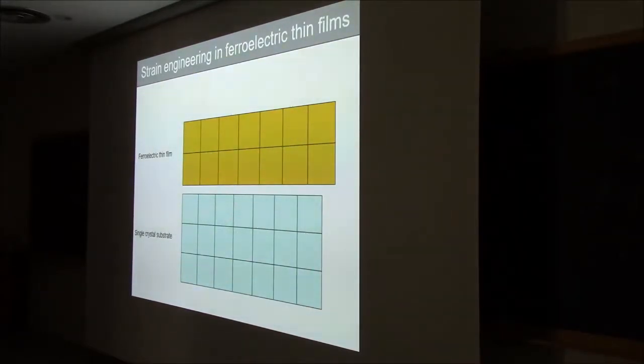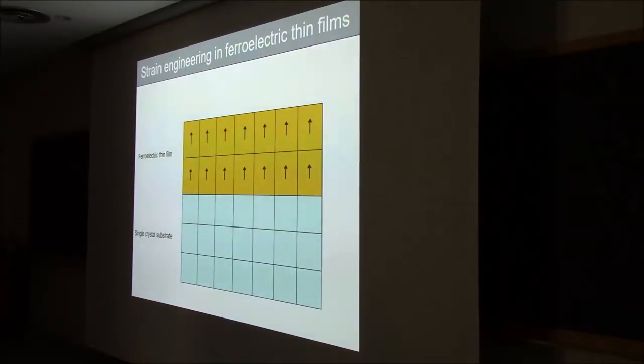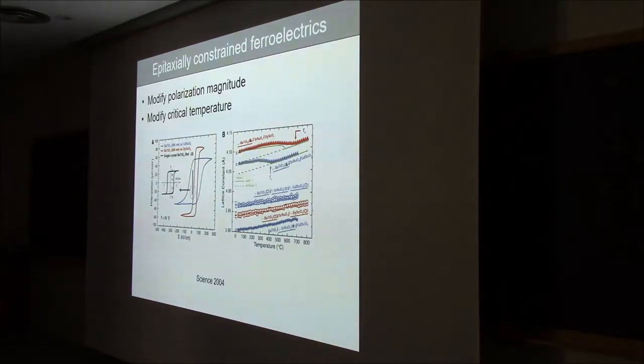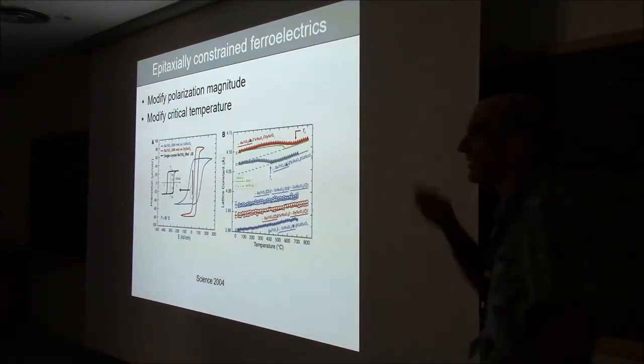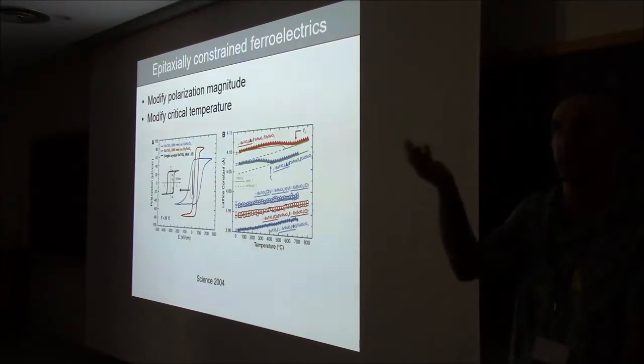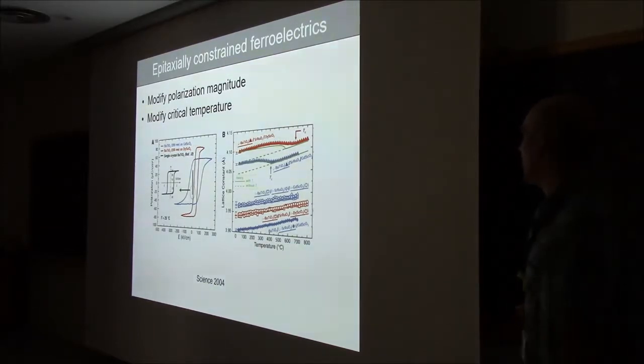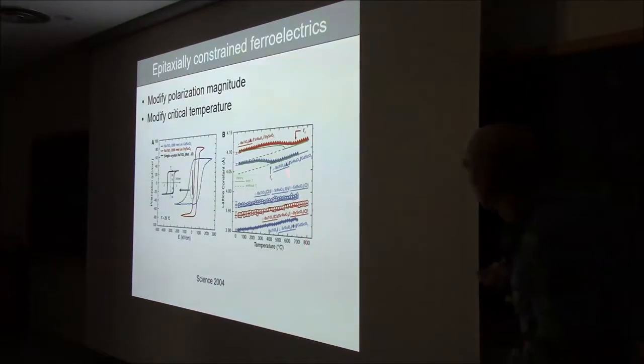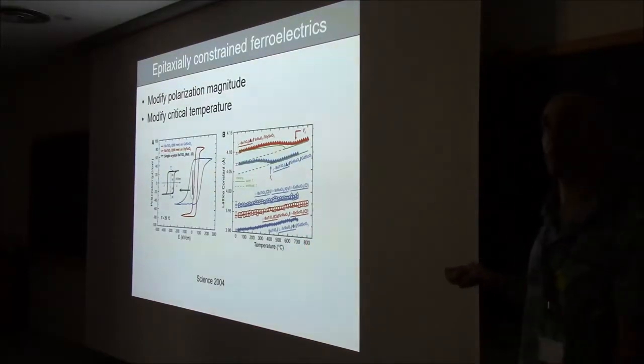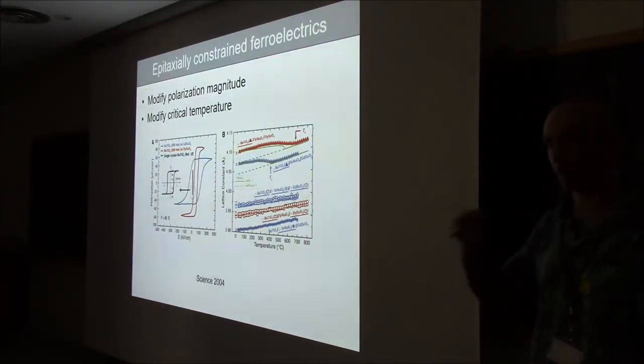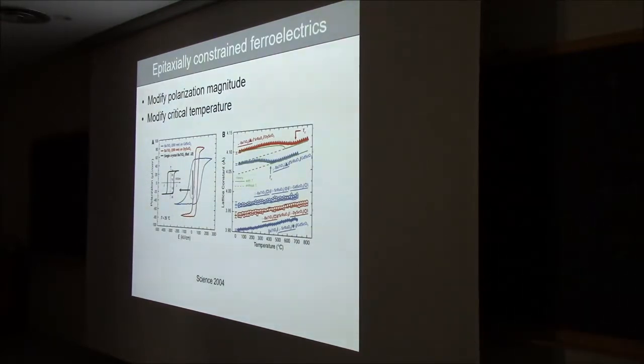You take your substrate, you take your ferroelectric film, you try to grow this epitaxially here, you force some constraint, you stabilize the ferroelectric phase at room temperature, even if your material would not have been ferroelectric at that temperature. Okay, and this really works. So you take barium titanate, the critical temperature of barium titanate bulk is about 130 Celsius. If you grow it on a scandate substrate, the critical temperature is of the order of hundreds of degrees Celsius. So it's a really powerful tuning of the transition that you get.